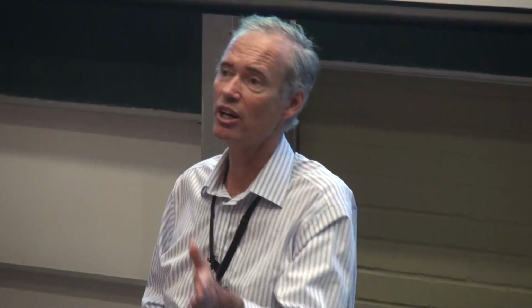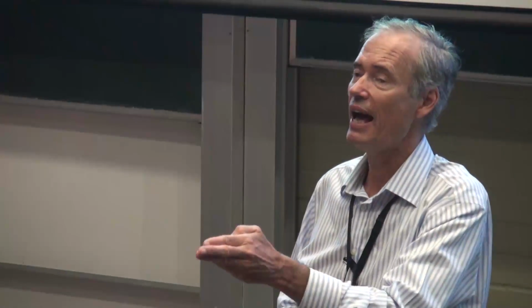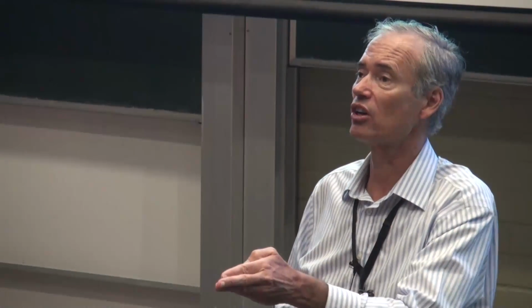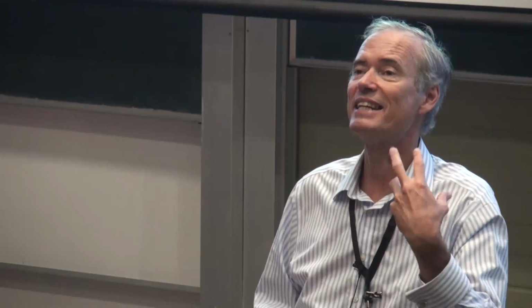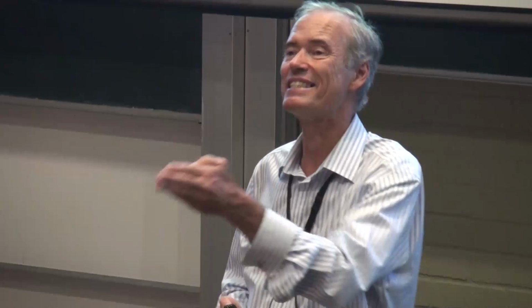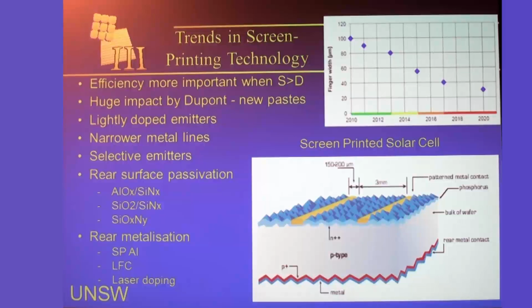And what that means is that, yes, you do heavily doped regions because there's clear benefit through having the heavily doped regions in localized areas, but they want a technique where the metal will then be self-aligned to those heavily doped regions, to take away all the risk of misalignment and all the associated problems you therefore get with yield. And so in large-scale manufacturing, we're still not seeing a large volume of product produced with selective emitters.